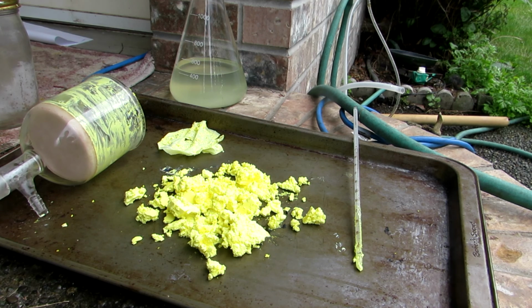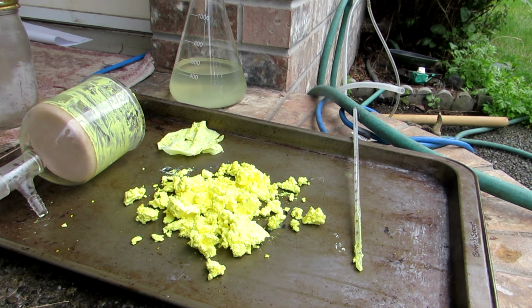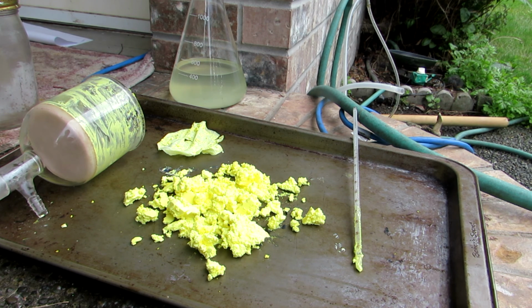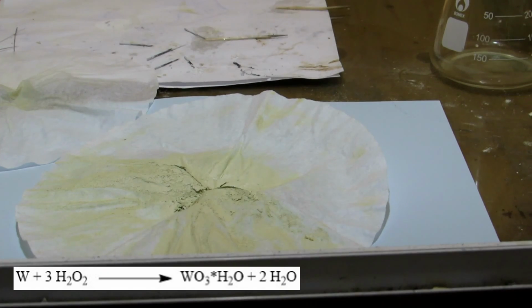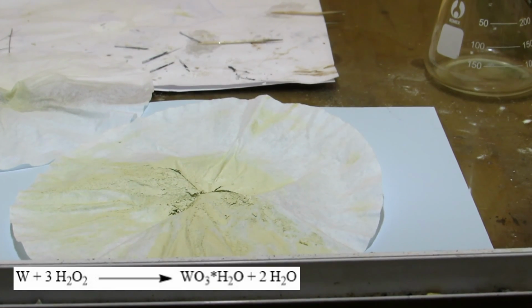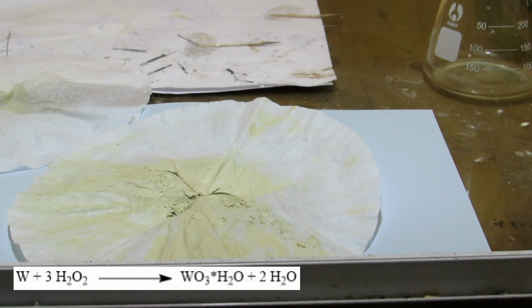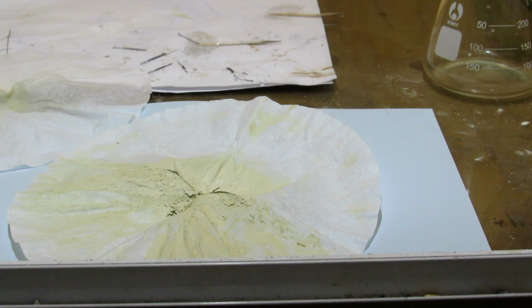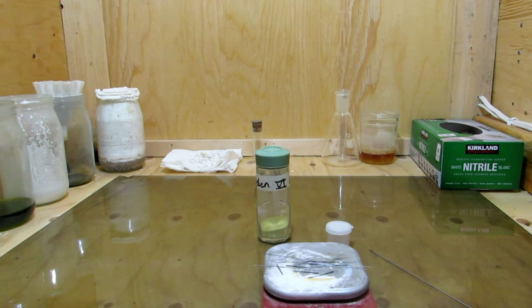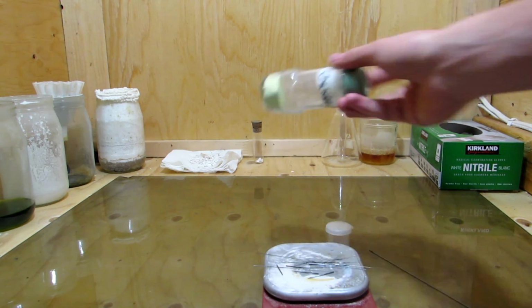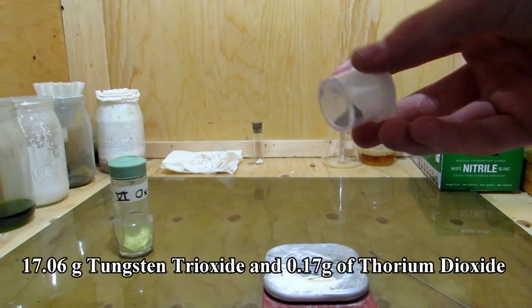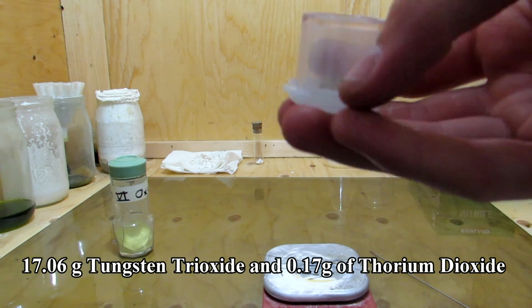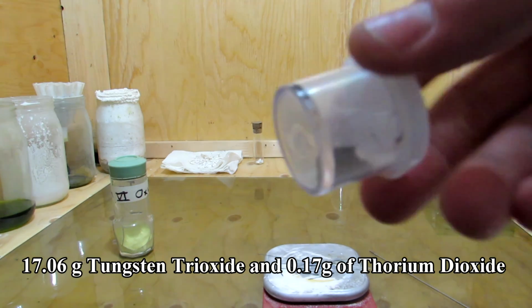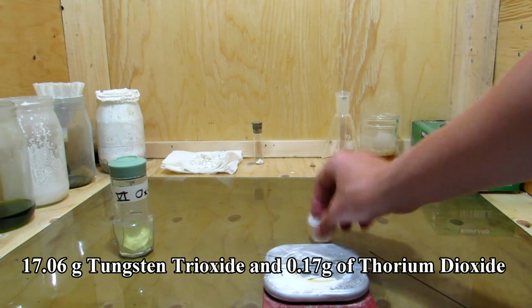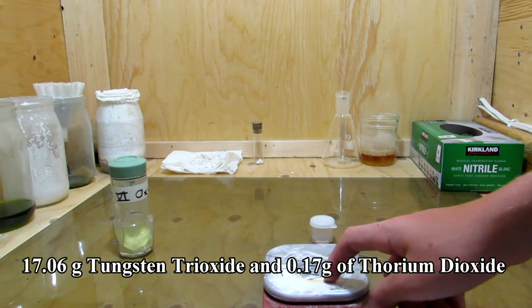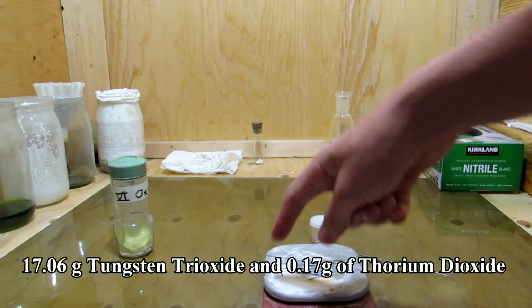The solution was vacuum filtered and then transferred to an oven at about 150 degrees Celsius to decompose the tungstic acid to tungsten trioxide. The decomposition occurs around 100 degrees Celsius. After sitting in the hydrogen peroxide solution for a few days, the thorium dioxide powder lightened in color as the residual tungsten contamination dissolved. The thorium dioxide was filtered and heated to about 250 degrees Celsius to fully dry the powder. After dehydrating the tungsten trioxide and thorium dioxide, 17.06 grams of tungsten trioxide and 0.17 grams of off-white thorium dioxide was obtained. From the 9 rods dissolved, 0.40 grams of thorium dioxide was expected, however, approximately 2 grams of tungsten didn't dissolve, and some of the thorium dioxide was lost during filtration, so the lower yield was expected.